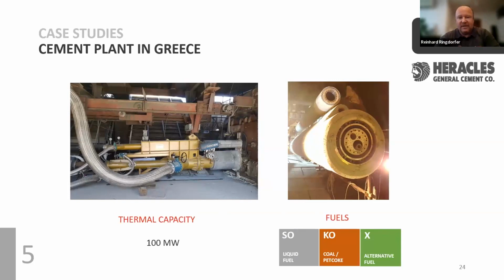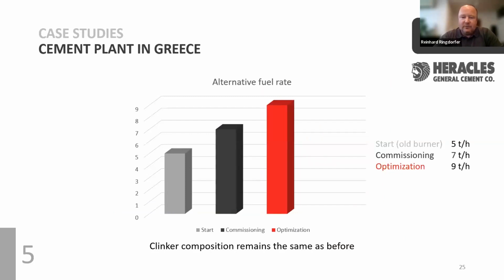In this case, the alternative fuel is only supplied through the satellite burner. Some other clients want to have, let's say, maybe a safety pipe through the main burner also, but in this case it was only the satellite burner. And the result was, with the old burner, 5 tons; after the commissioning, the guaranteed 7 tons per hour were reached. And after optimization, of course, depending on the material, they can go up to 9 tons per hour.